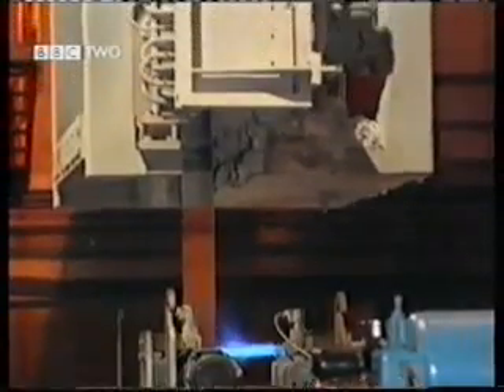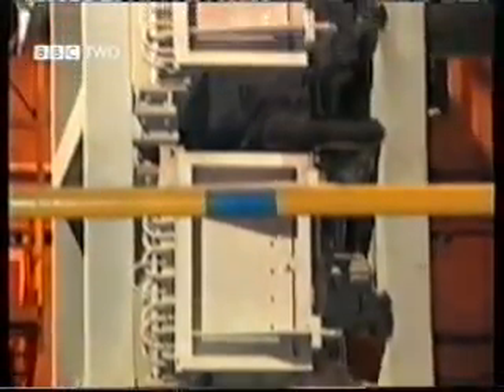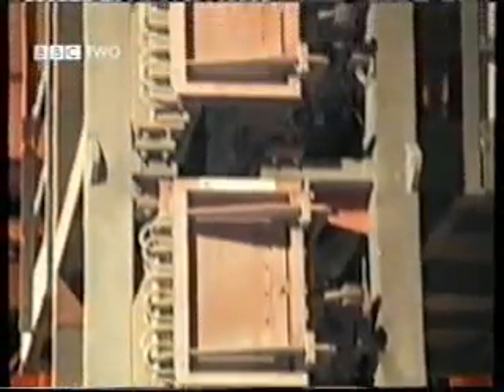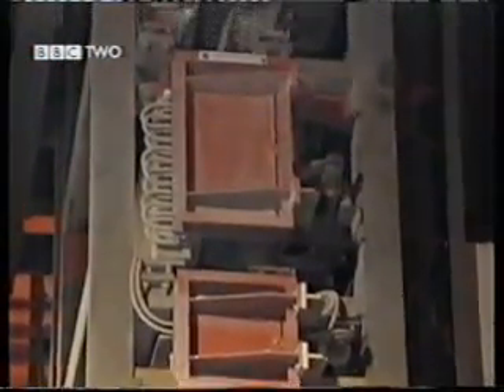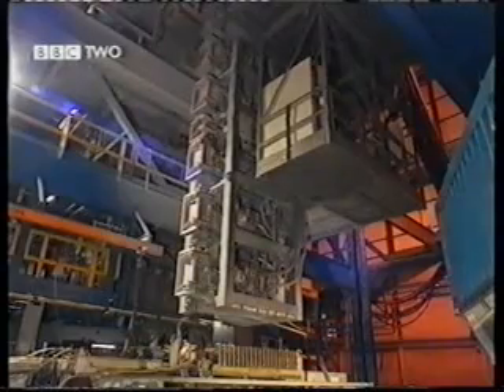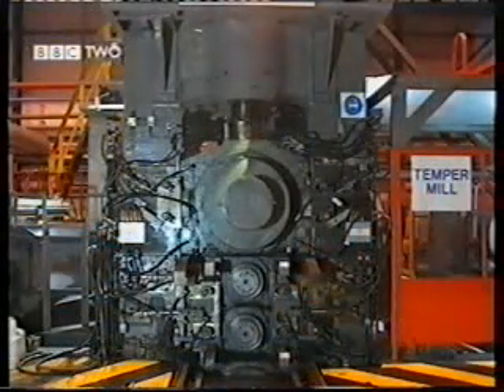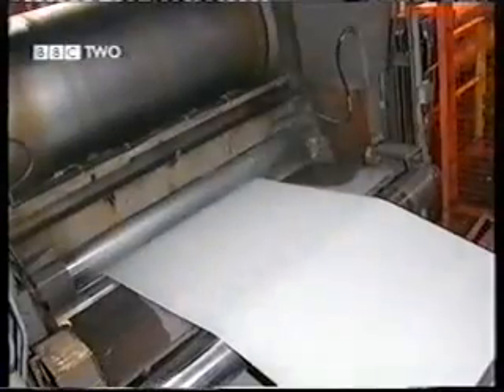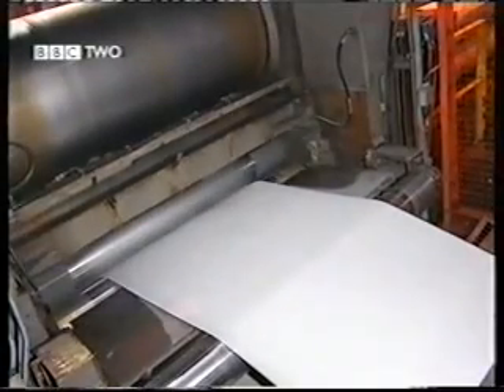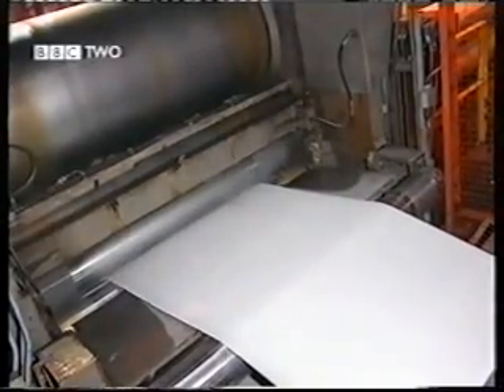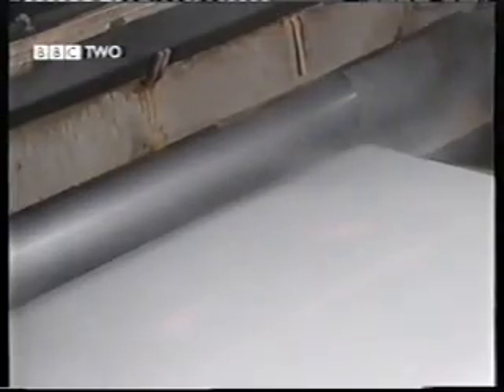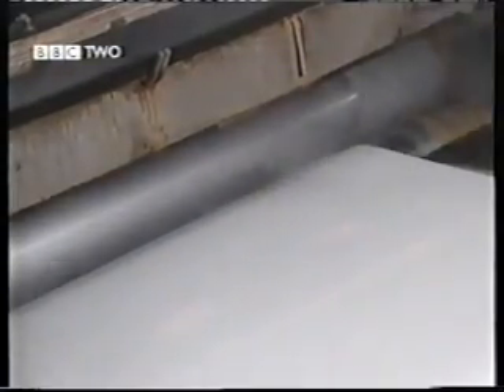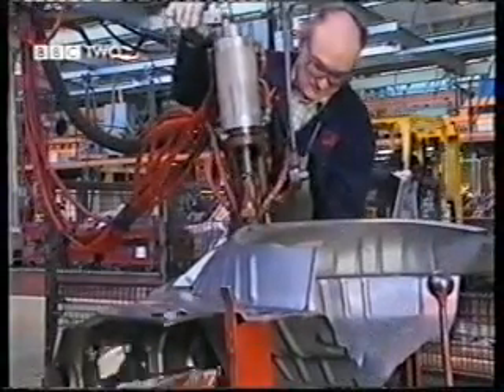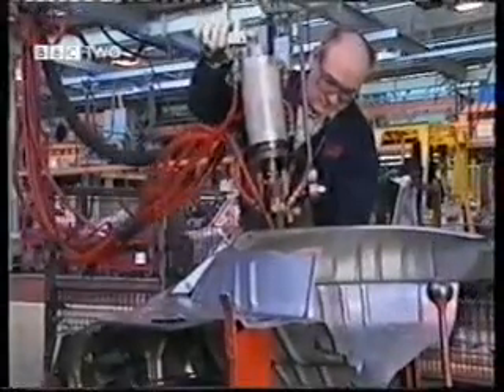Then, by careful heat treatment within a vertical furnace located above the zinc bath, the zinc coating is converted into a layer of iron-zinc alloy. In the tempering process which follows, fissures develop in the surface, and these help the paint key into the coating. Also, within the alloy, a hard phase develops. And this means that less zinc is melted out of the surface layer when it's spot welded.